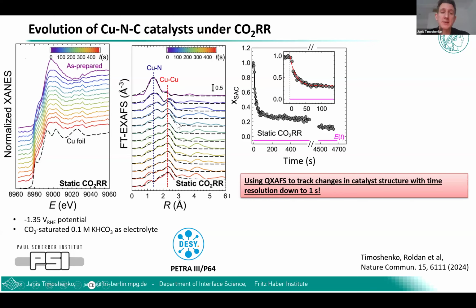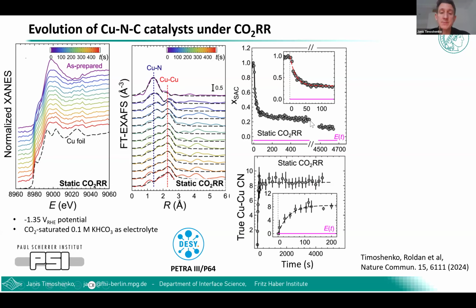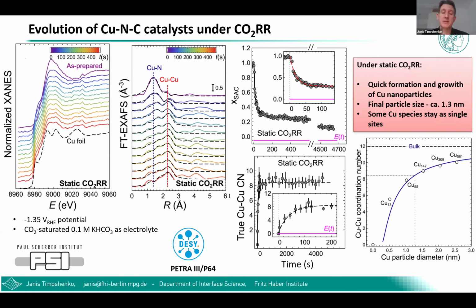But if we manage to extract also EXAFS data and do the fitting of EXAFS spectra, we can extract information about particle sizes. Specifically, what we extract from EXAFS is the average copper-copper coordination numbers, which we see are clearly changing a lot during this experiment. So we start from 0 and end up with something about 8 point something. And then using simple models, we can link this average coordination number, which basically characterizes your surface to volume ratio in your nanoparticle, to specific particle sizes in nanometers.